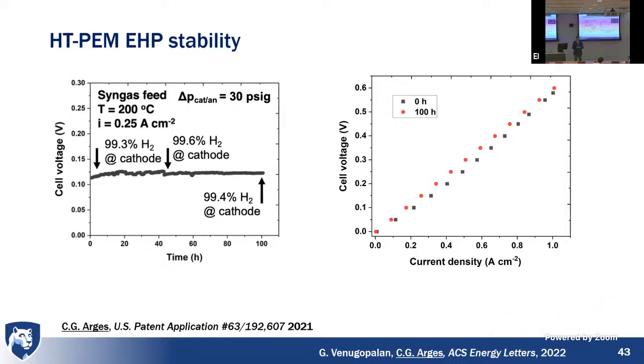Complimenting you on your talk. I was wondering if you measured the electronic conductivity of the binders, and how stable are your binders? Great question. We have not measured the electrical conductivity of the binders, and on the stability side, we have the slide up, where the binder was in the system. So we were at 100 hours at 200 degrees C and running, with, I can't remember, 120 millivolts on the cell.